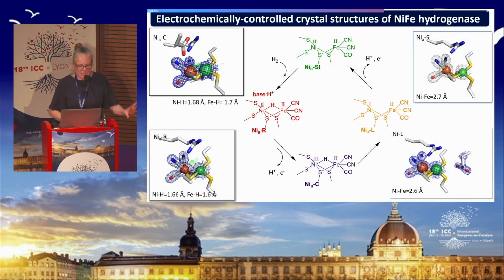So to summarize this part of it, what we've really got here is a series of structures that we can now paste onto this cycle that otherwise is just a series of ChemDraw images pasted together from lots of different pieces of work. We now have structures that show us what's happening here. They show very minimal movement, but this really key flick of the glutamate, which is key to fast proton transfer within this very finely tuned catalytic cycle.